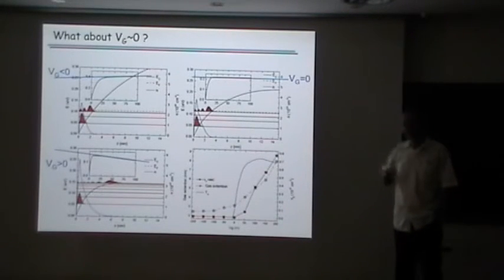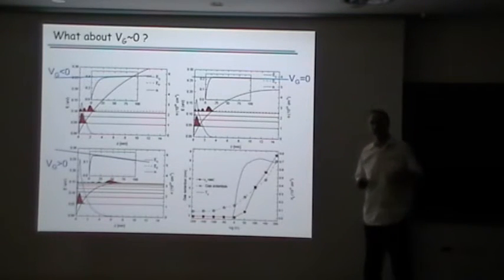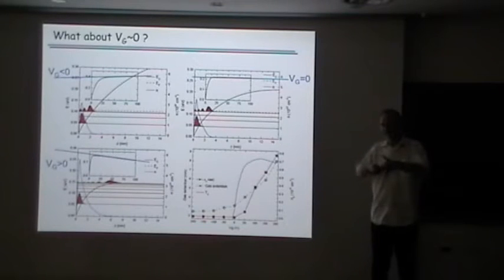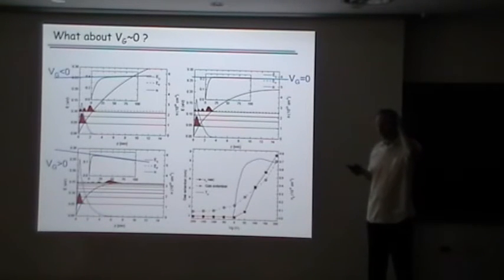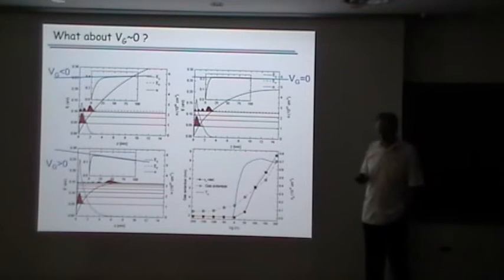And I think the electrons are mainly in the strontium titanate, and all the conducting materials we have in hand behave exactly the same way as the others when you have a band insulator and a band insulator. I just want also to stress the phase diagram by Okamoto and Millis, which is very exciting: lanthanum titanate, strontium titanate, where you expect something. But for their paper, I think the Mott nature of lanthanum titanate also didn't play a role, from what I remember. I had this impression actually that it was essentially the same physics, as though it's simply two band insulators.